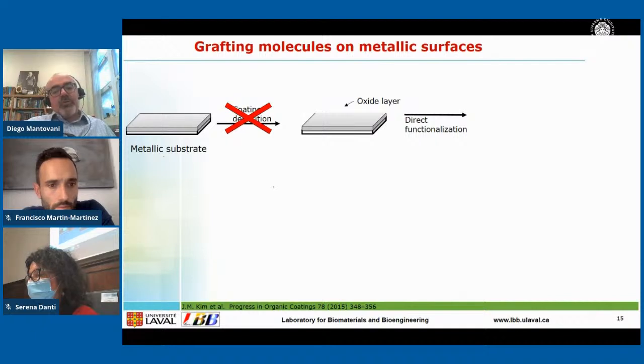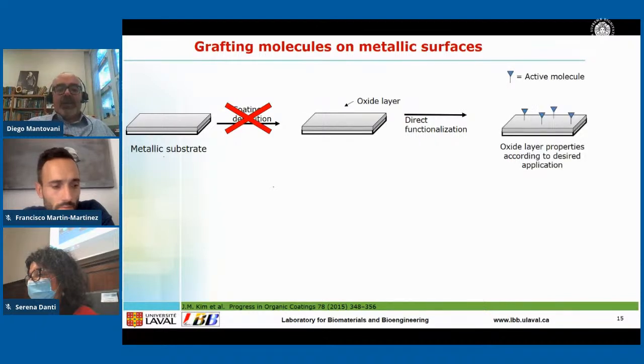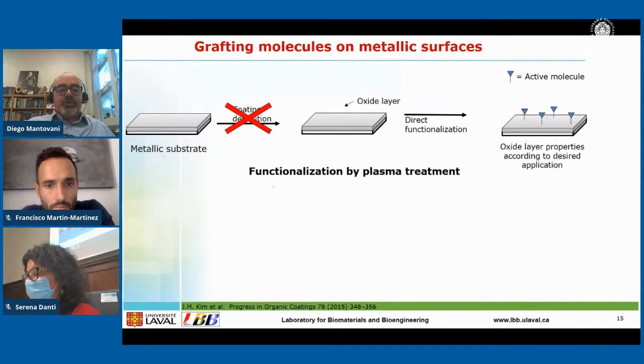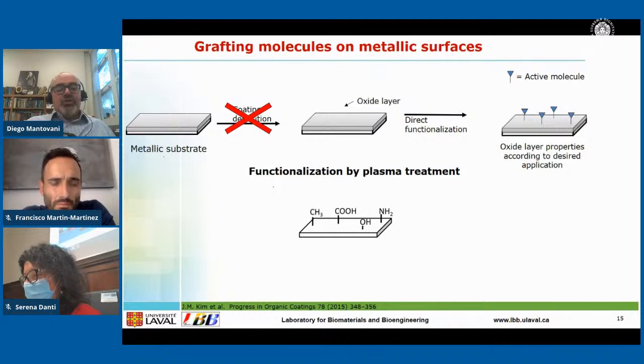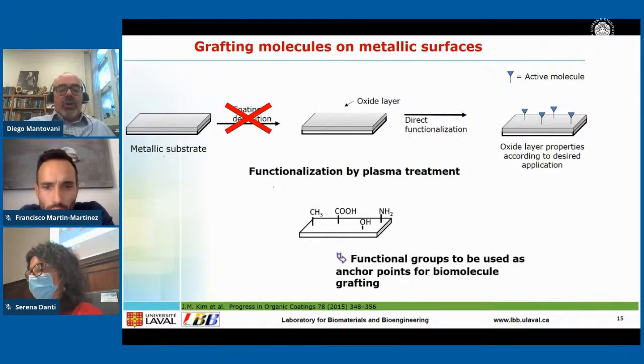Our approach was to explore direct functionalization by plasma. This resulted very original. No one has ever published or reported work on direct functionalization. Direct means taking the metal, putting it in a plasma reactor, and creating functionalization groups by plasma treatment. Depending on the gas that you use in the plasma, you can fix carboxyl groups, amine groups, or other groups.